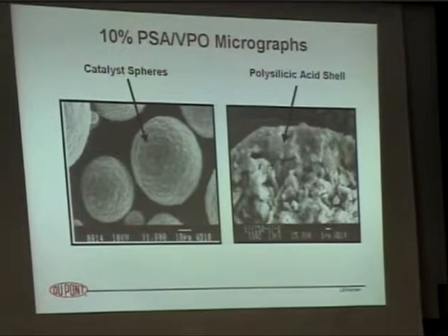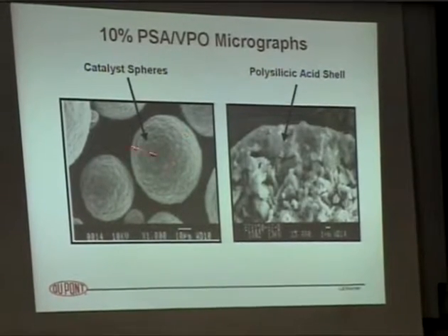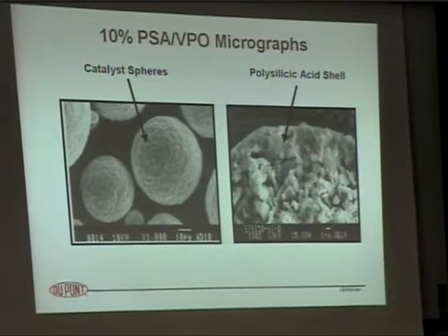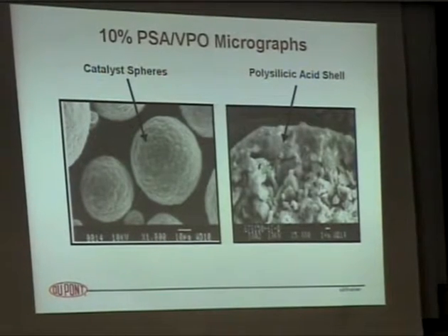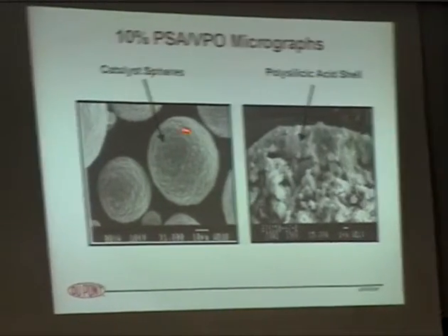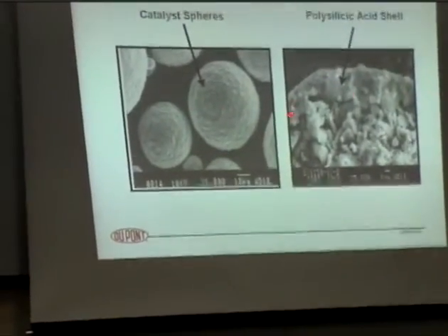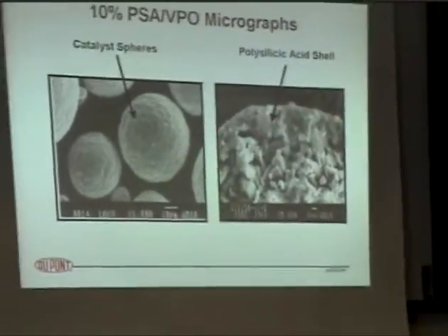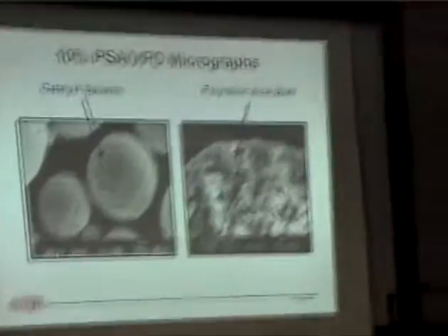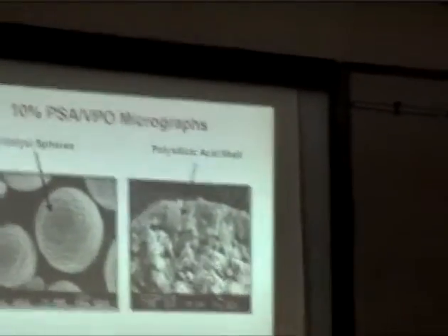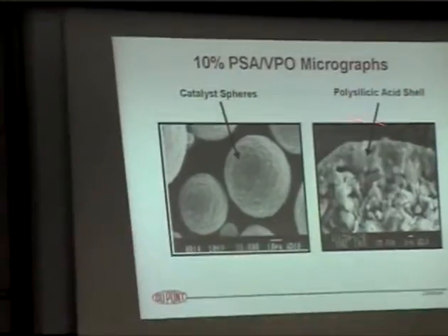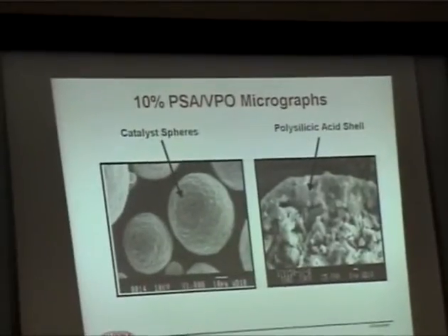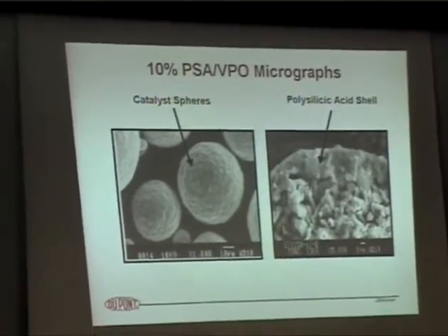This shows an electron micrograph of the nice, beautiful, round VPO particles coming out of the spray dryer, just set up just beautifully for fluid bed operation. There is this very porous silica shell on the surface, and that encapsulates like a tennis ball, with the outside surface being the silica and the inside being chock full of VPO, porous VPO, very soft catalyst. So the butane diffuses through that outer shell, reacts, and the maleic anhydride comes back out again.